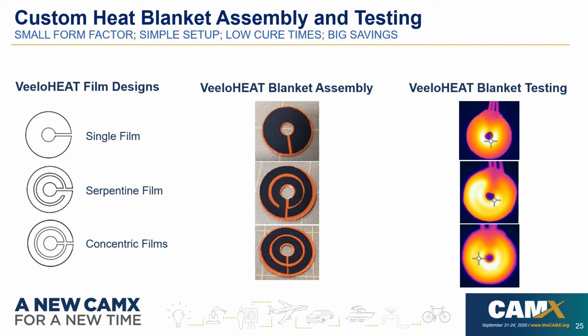We took some IR thermographs. You can see that we did see the anticipated result with the single film design, where the interior of the blanket is hotter than the outer diameter of the blanket. In certain applications, this might be preferred, but for our internal need, it was not. The second two designs, the serpentine and the concentric film design, had relatively similar temperature deltas, although the concentric film seems to have the best overall uniformity.